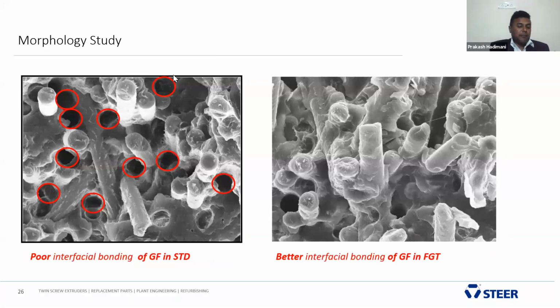Next slide. You see the magnified SEM analysis here, and on the left-hand side, again the standard technology, you see the fiber pull out. When the tensile specimen experiences the load, what happens? The fiber just comes out from the matrix. But in the FGT technology, you see that the fiber is completely coated and it is retained in the polymer matrix, so that it increases the mechanical property. Next slide.